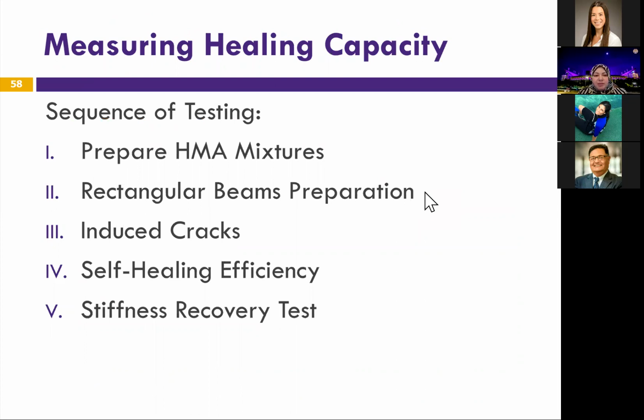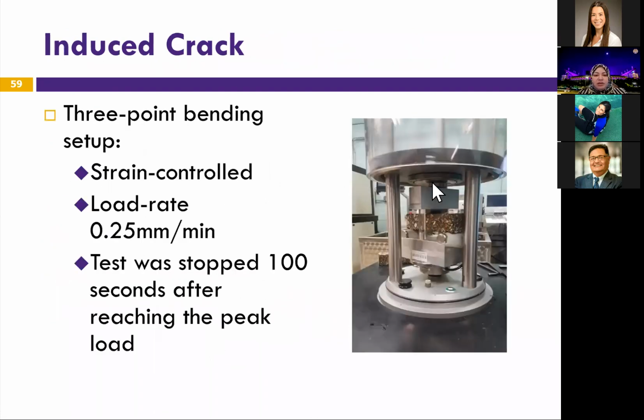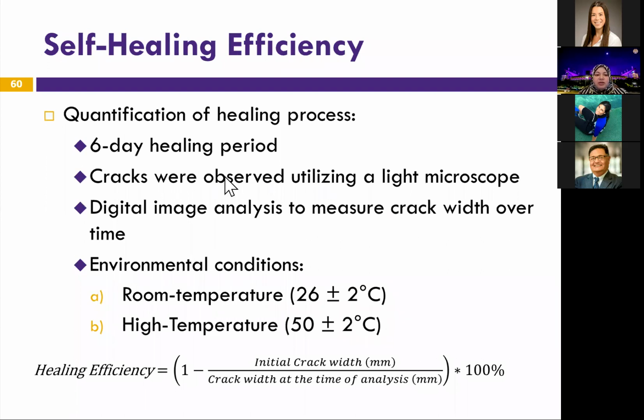Then we measured the healing capacity. We prepared hot mix asphalt beams. We induced cracks in them and then left them to heal. And then after that, looked at how the cracks are closing over time, or the size of the cracks decreasing over time. And then we also measured the stiffness before and after to get the stiffness recovery. So as you can see, here is the beam being tested. It's a 3-point bending, strain controlled with a load rate of 0.25 millimeter per minute. The test was stopped 100 seconds after reaching the peak load. So it just induces a crack.